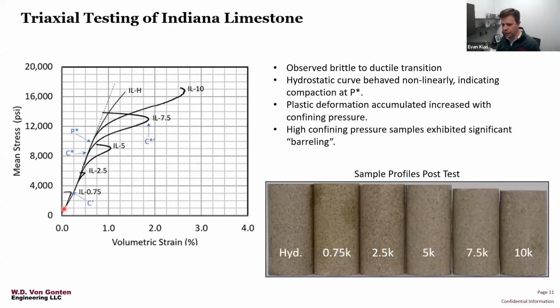You can do things to mitigate the presence of these cracks by performing a few hydrostatic samples before the triaxial stage. That's in fact what we did with the Vaca Muerta samples in preparation for creating the constitutive model. Those hydrostatic cycles allowed us to see how the pores are changing, and the difference between when pores are closing and consolidating under stress they haven't seen before, versus unloading. In soil mechanics this is the topic of unconsolidated versus consolidated deformation. This is all very different from that initial portion of the test where you're just closing microcracks, a necessary evil you need to go through in order to restore the sample to its in situ condition and test the properties you want to test.